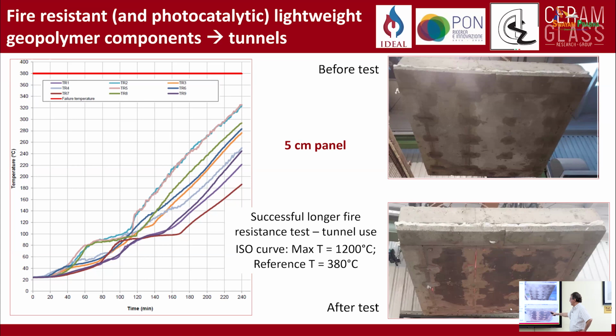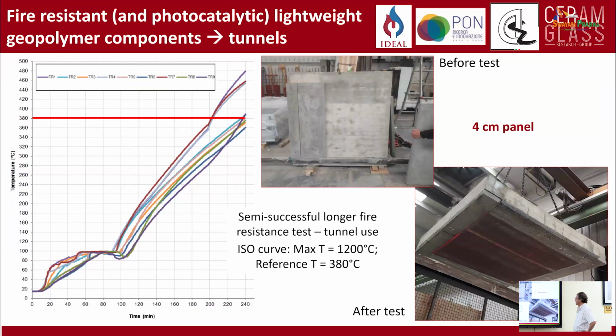It was not possible to print a panel occupying the entire volume. So this is based on 2 adjacent panels, but you can see that the panels can also be anchored to the other structures. Because of the porosity in the board, you can drill through the board without cracking. This is the 4 centimeter panel. In this case, we were aiming at 240 minutes, and you can see the crossover at around 180 minutes.